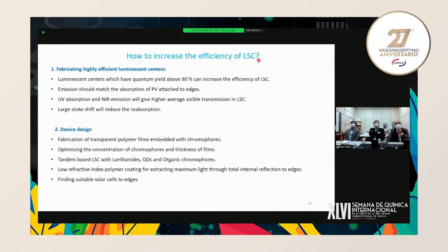So how to increase the efficiency of LSC? First of all, fabricating highly efficient luminescent center. Luminescent center means chromophores. They are important. We should have above 90% quantum yield, then it will be better. And also emission should match the absorption of PV attached to edges. UV absorption and NIR emission will give higher average visible transmission in LSCs. If we have large Stokes shift, then we can reduce the reabsorption and increase the efficiency in LSCs.